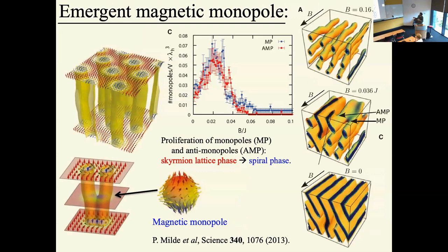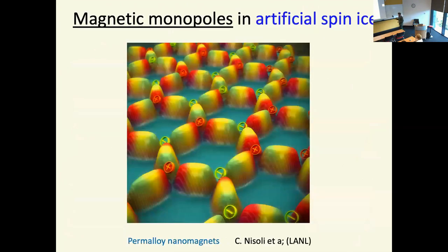So this is one example of monopole observation, but there's a whole field called artificial spin ice. So how should I go back? 1930s again, Linus Pauling. You have a water molecule, H2O. So you have O, you have 2 orbitals, but there are 2 empty orbitals here. If you calculate the entropy of a water molecule, it is non-zero, and this is because there's frustration. You can create the same thing in nano islands of permalloy, in which I will have two magnetic spins going in, two out, and you create a configuration in which there's magnetic frustration. That's called artificial spin ice in very simple language.